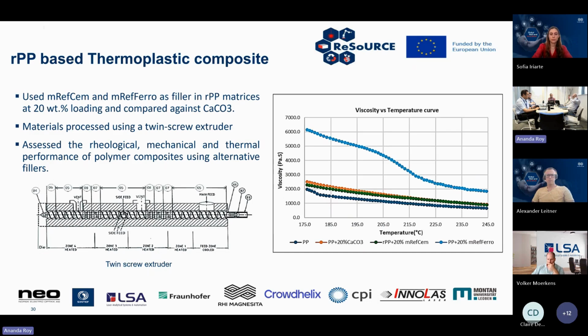Last but not least, within the polypropylene system, we tried to include these fillers and see their performance again within the same structure of the mechanical or thermal establishment. As you can see with the viscosity graph, it's quite substantial that the MREF ferro especially shows a very sharp increase in viscosity, almost 3 times the other fillers within the system. The pronounced rheological response of the MREF ferro filled composite highlights that its potential as a reinforcement agent is again very high, with higher melt strength and also dimensional stability, which is required within the polypropylene system.